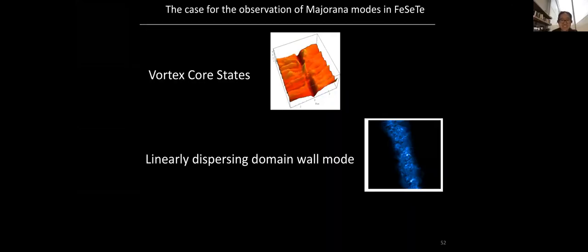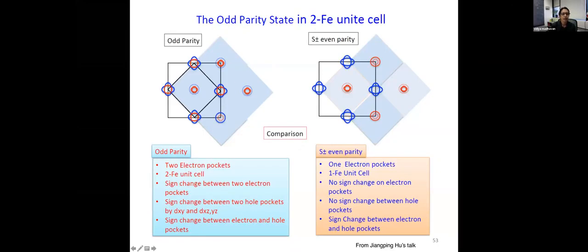Okay, so I just want to show you something really interesting. This was Jianping Hu's prediction that for these iron-based compounds, we know there's a lot of evidence that we have an S plus minus order parameter, where the order parameter has a phase shift between the electron and the hole pockets. But if what he predicts is correct, which is what we based our analysis on, you also expect to see a pi phase shift between the two hole pockets at the gamma point.